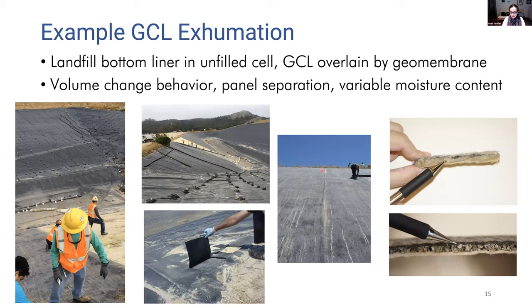This figure is looking up towards the top of the hill, and in this case, we're seeing the GCL material. The panels had shrunk, and we can see gaps between the panels and the underlying soil is exposed. The GCL is not really functioning properly as a barrier material anymore due to the presence of these gaps in the system. We also saw that there was a lot of material carried down slope, meaning there are a lot of streaks of bentonite on the top surface of the GCL, and we actually observed accumulation of the bentonite at the bottom of the slope in some locations in this entire cell that was being exhumed.